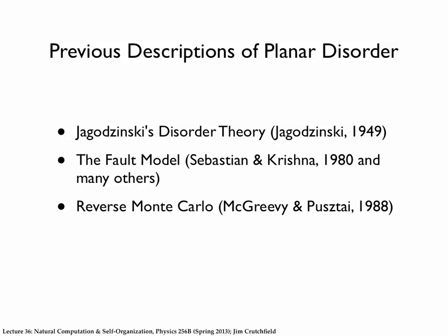And it's called reverse Monte Carlo modeling. Basically, what you do is you build a box. Computationally, in a computer, you build a box and you toss in a bunch of stuff. And you have some type of experimental signal that you get from your real sample, and you want to somehow move the atoms and the things so that they're in an arrangement that gives you the same experimental signal that you see out there in the lab.